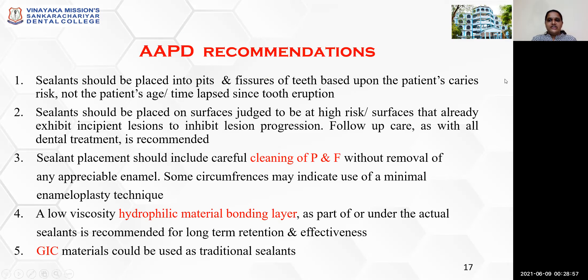The AAPD recommendations for the placement of pit and fissure sealants: sealants should be placed based on the patient's caries risk and not on the patient's age or time lapse since tooth eruption. Sealants should be placed on surfaces judged to be at high risk or surfaces that already exhibit incipient lesions to inhibit the progression of the lesion. Follow-up care is recommended. Sealant placement should include careful cleaning of pits and fissures without removal of any appreciable enamel. A low viscosity hydrophilic bonding layer is recommended for long-term retention and effectiveness. GIC materials could also be used as traditional sealants.